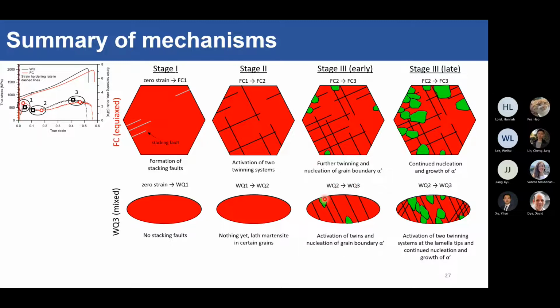In the water quench sample, finally, you get some twinning, and we know that the twinning stress increases with decreasing grain size. And this lamellar thickness is only about 100 to 200 nanometers. And that's why twinning was delayed to a much higher global stress and strain. So finally, it does twin, and then you get martensite growing off the grain boundaries, and then they work their way into the middle. So at this point, we start to think whether the grain boundary area to volume ratio actually plays a part with martensite formation.